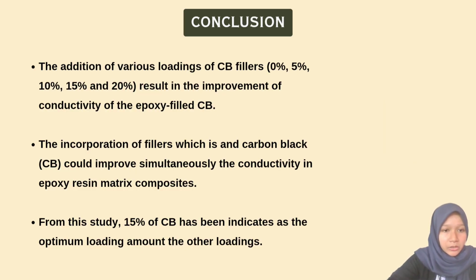It can be concluded that the addition of various loadings of carbon black filler results in the improvement of conductivity of the epoxy-filled carbon black. The result of electrical properties reveals that the incorporation of filler, which is carbon black, could improve the conductivity in the epoxy resin matrix composite. From this study, we can conclude that 15% of carbon black has been indicated as the optimal loading among the other loadings.